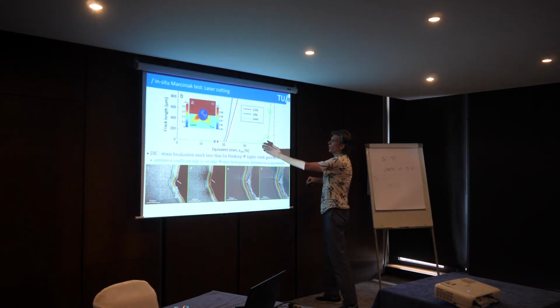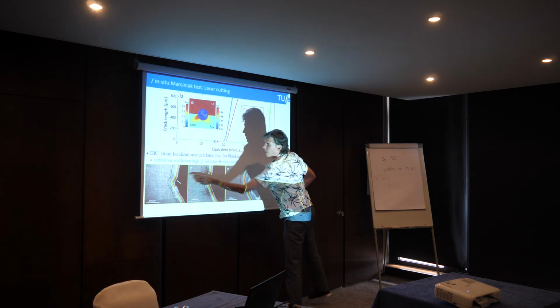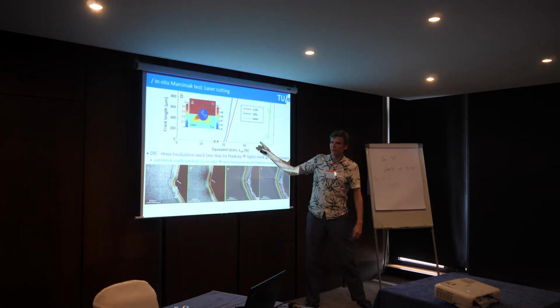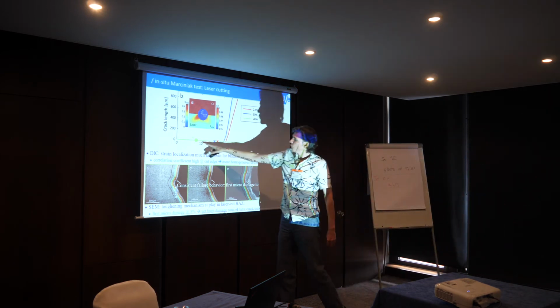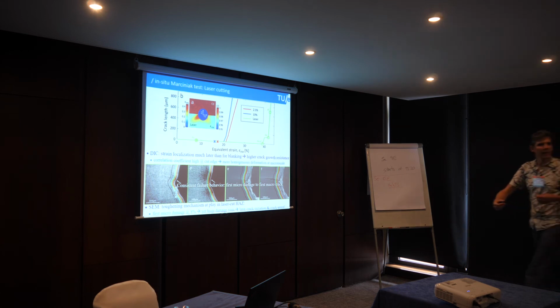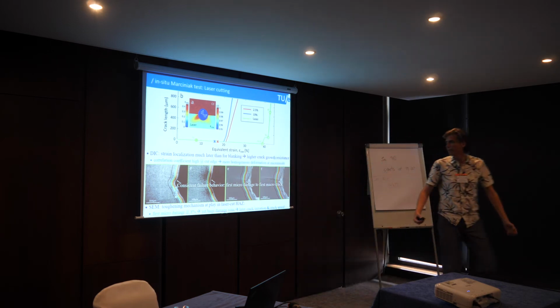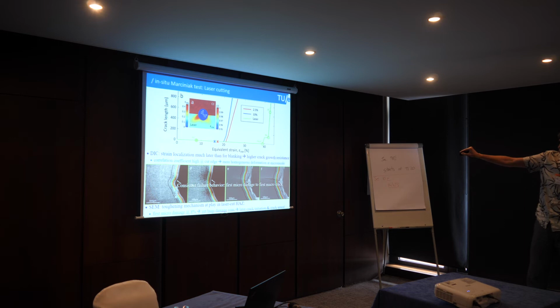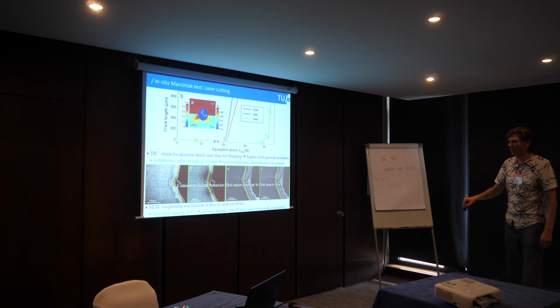Well, you would think that because the crack would propagate at a much later state, this initial point of damage would also be somewhere on the right. Oh, but look at this, it's completely on the left. So the first damage that we're seeing is happening much earlier than in the case of blanking. But it actually takes a huge amount of strain to get this crack propagated. So it is consistent. This first damage evolves into a major damage, into the first crack propagation. That's basically here, outside of the screen.